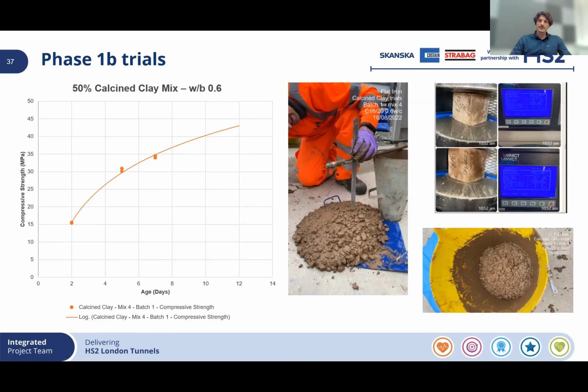We had to do a little bit more work in terms of achieving the required workability. We can see here from the slump test, the workability might be fine, but there might be a little bit of segregation. So we are working towards that. But strength-wise, which was our main concern, we're performing much better than what we initially anticipated. Next slide, please.